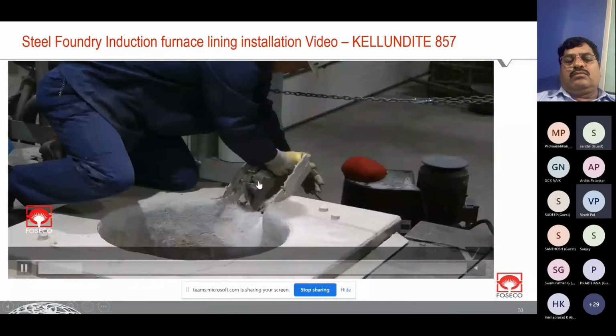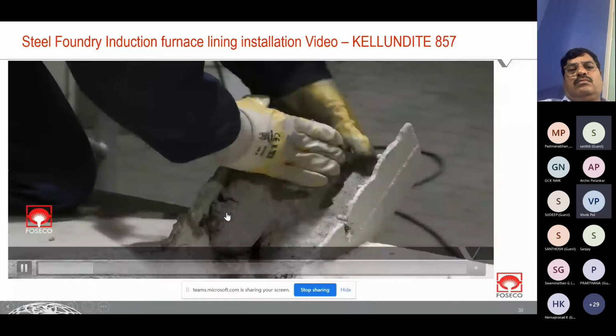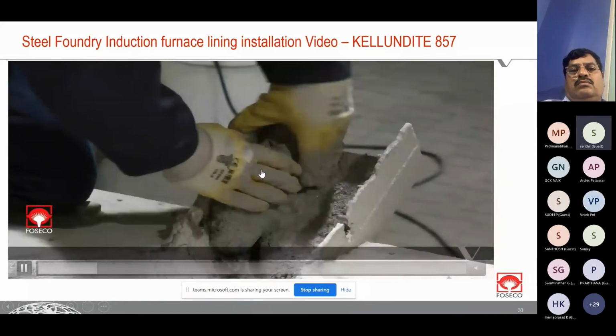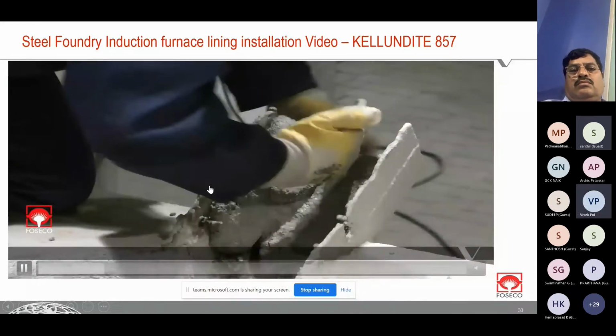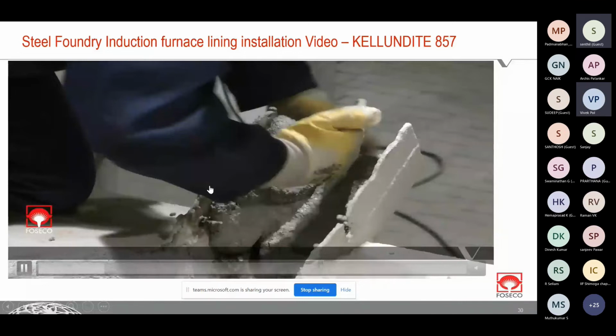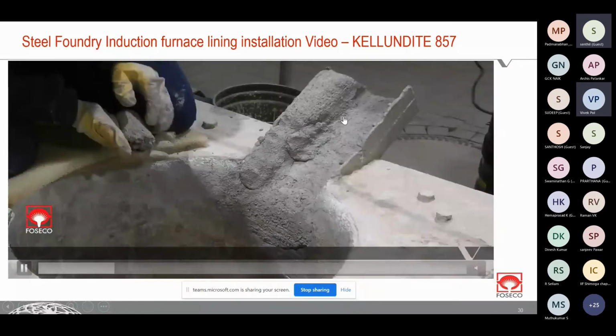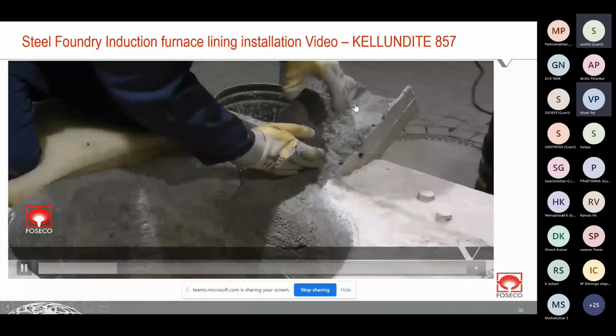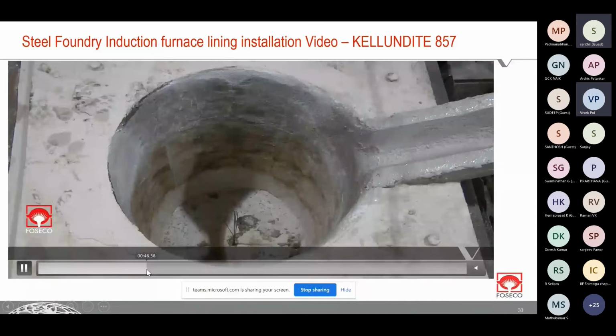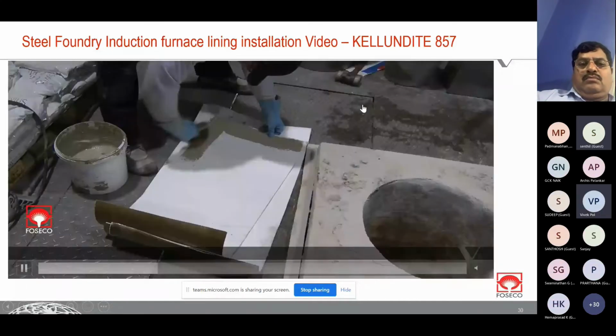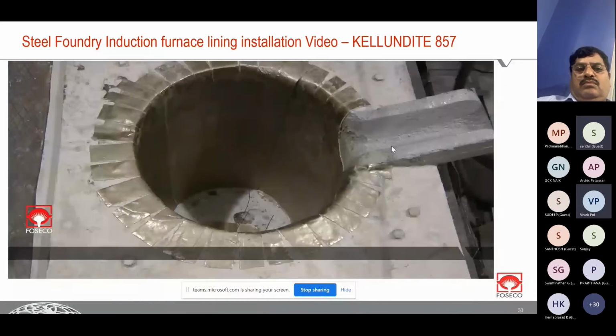So again, they have started with the blue ram on spout. We always recommend that during lining installation, the first installation should be on spout, and the material should be blue ram HS, and then we can do this furnace lining, main body lining. For that, before lining, just as a protection for the coil, these mica sheet papers are used.